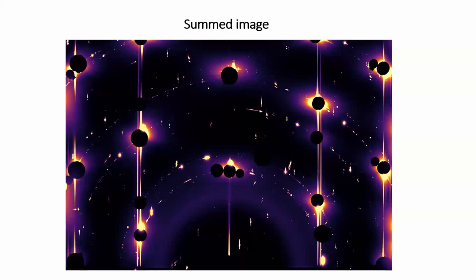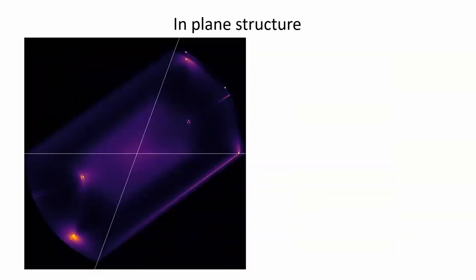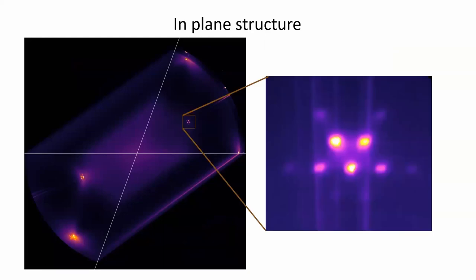So if you sum all these images up, then you see that you have the crystal truncation rods here, and then you have the herringbone reconstruction here. They are all over the place, and it's a three-dimensional representation of reciprocal space. If we cut it maybe at low L, we get a picture like this, and if we zoom in, we get a picture like this, and this is the herringbone reconstruction with three rotated domains